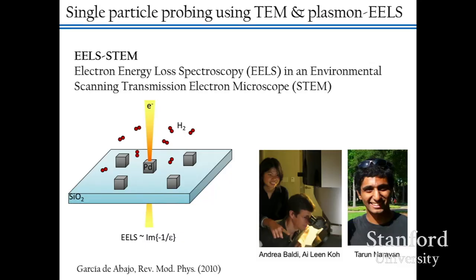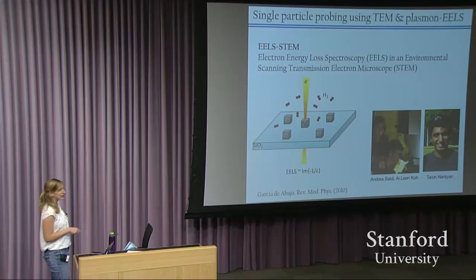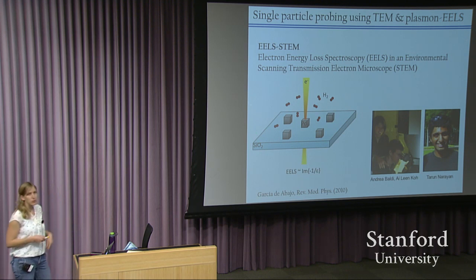So the technique that we decided to rely on is in-situ electron microscopy and spectroscopy. In particular, we're going to rely strongly on a technique called electron energy loss spectroscopy in an environmental scanning transmission electron microscope. It's kind of a mouthful of words, but it's actually a very easy technique to understand. First of all, we synthesize palladium nanoparticles. We disperse them on an electron transparent substrate. And then we come in with an electron beam.